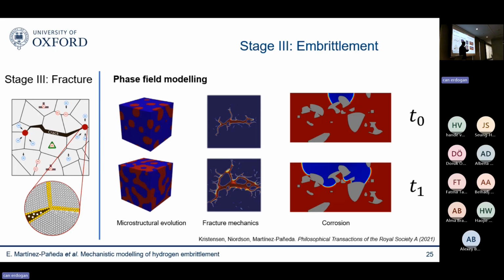And you can see why here, this is the outcome of the simulation. This is a hydrogen fracture process. That's why you see such a funny crack branching process. You can see that the model is able to capture very complicated stuff, branching, nucleation of secondary cracks, coalescence of multiple cracks. And also recently, although I won't have time to discuss it today, we have shown that the phase field paradigm can be used to simulate corrosion. You can use the phase field to track the evolution of the corrosion front, to track the interface between the aqueous electrolyte, the seawater, and the metal, for example, right? The evolution of this electrolyte metal interface. But I'm going to focus today on fracture.